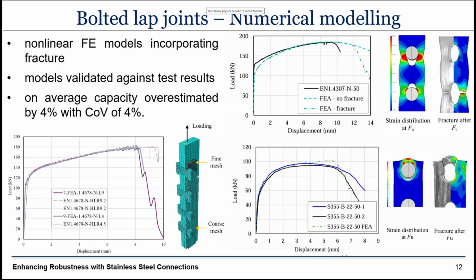After we completed the tests, or actually during doing the tests, we also did some numerical modeling. So we developed and validated numerical models against the experimental results. The failure modes in all cases were perfectly replicated. On average, the net section fracture models overestimated the strength by about 2% with a small coefficient of variation of about 4%. And the bearing models overestimated the strength by about 5% with a coefficient of variation of 1.8%.